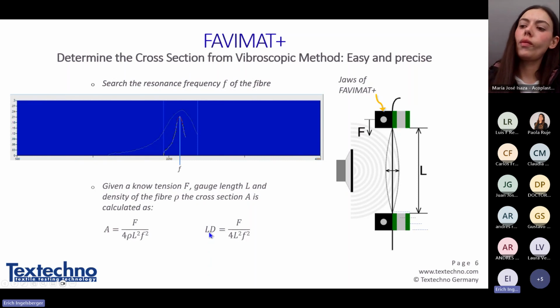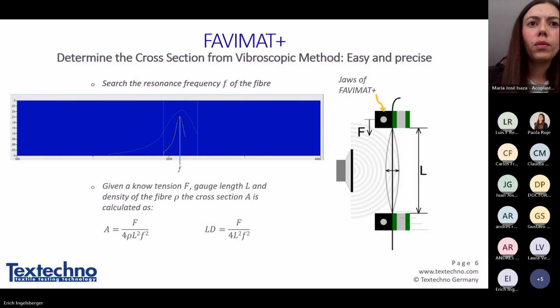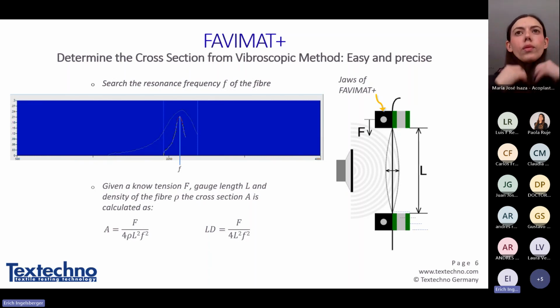Linear density is nothing else than weight per unit length. This is measured in tex in the textile world, which is gram per 1000 meter fiber length. From this linear density, if we include the density of the carbon, which is usually 1.8 gram per cubic centimeter, and assume a cylindrical fiber, we can then calculate the cross section.